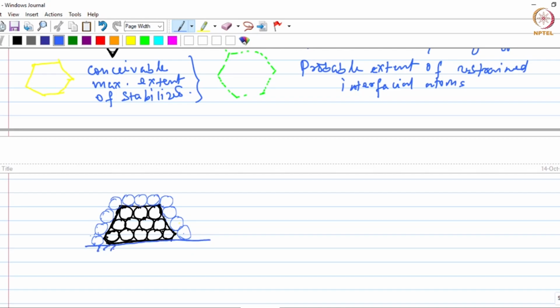So this is basically the TiB2 surface. And here the titanium atom has actually diffused to this interface between the boride and the melt. Okay, so this is the titanium atom, right? And with the help of this segregated titanium, the atoms around it are all fixed, the aluminium atoms.